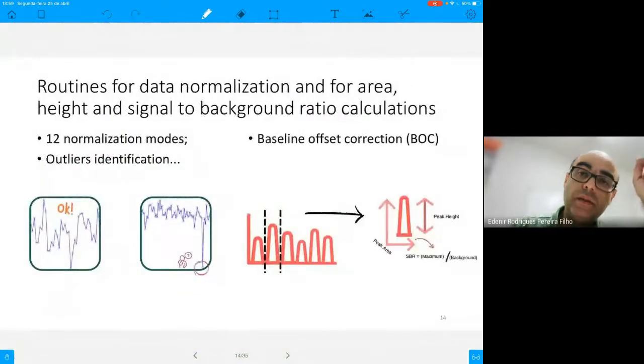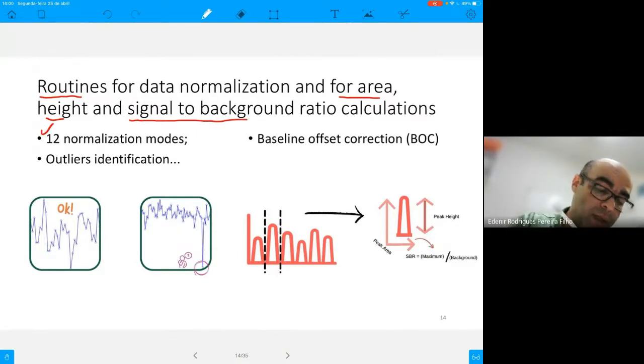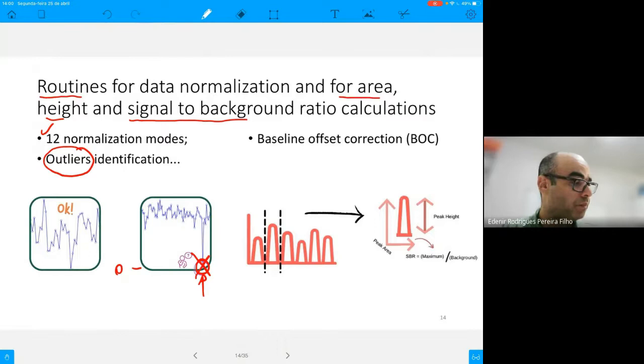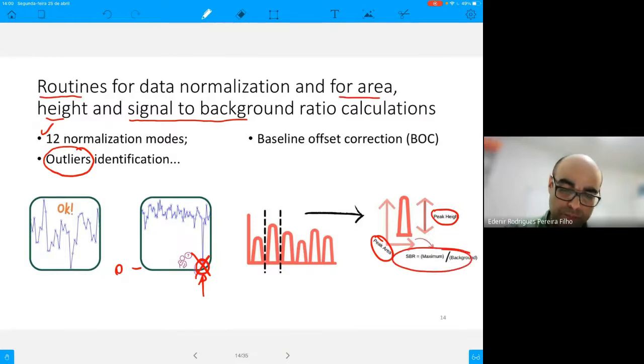Okay. In my research group, we also developed several routines for data normalization, for area and height calculation, and also to calculate the signal to background ratio. Okay, we have the normalization, and with this normalization, we can identify outliers. For example, we have here a sample, and here we have the signal 0, for example. We can identify the sample and remove the sample from the spectrum. And also we can calculate peak area and peak height of the samples and signal to background ratio.